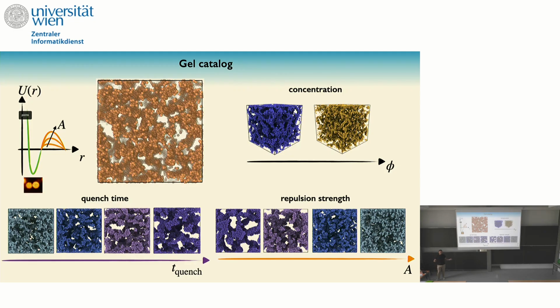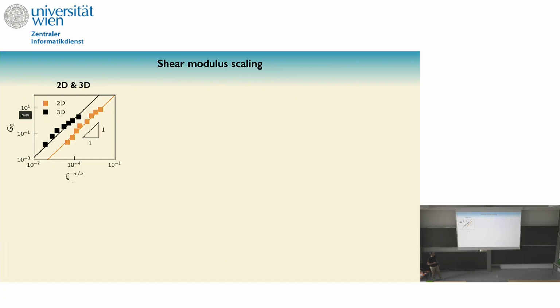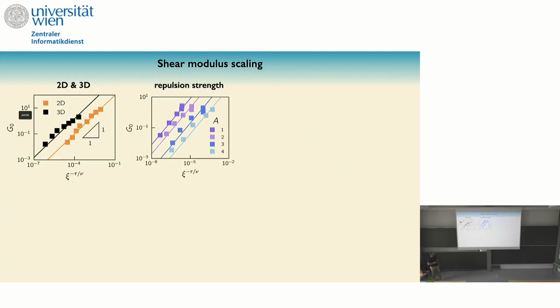So can we understand the elasticity or rheological properties of this system within this framework? And the answer is yes. Now I'm measuring the modulus as a function of this length scale. You see that it works very well in 2D and 3D, provided that it's dominated by the bending. If I add electrostatic interaction, I would also recover the same scaling, but you see that the curves are parallel. All the curves here are parallel. They do not fall onto a master curve, right?